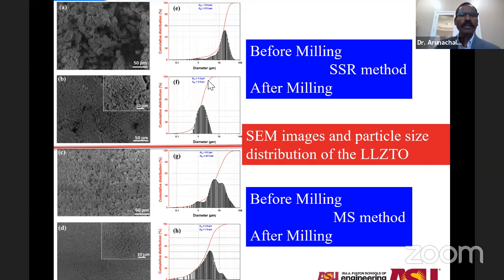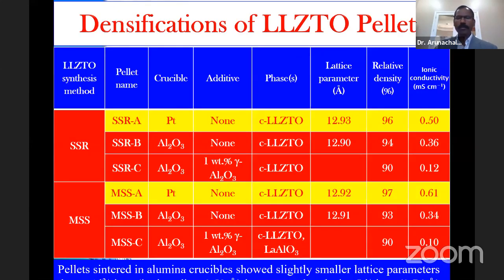Then we looked at the particle size and also the distribution. I don't think you can see the values here, but the diameters at 50% and 90%, the particle sizes, are relatively larger for the solid-state reaction. But in the molten salt method, the particles had a bimodal or even trimodal distribution before milling, but after milling, only a few percent were larger particles and the rest were relatively smaller. Then the powdered materials were made into pellets of about 10 millimeter diameter, and sintering is a major process step in making the pellet highly dense.